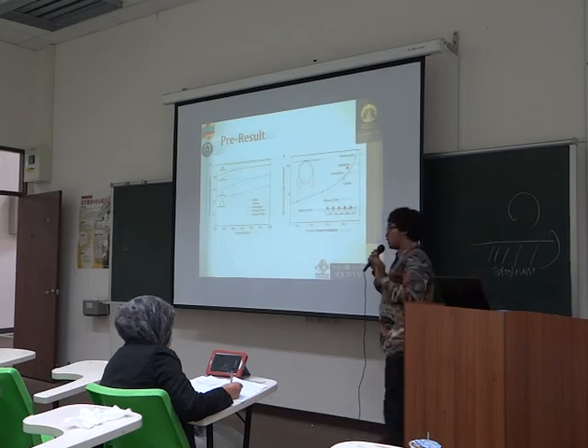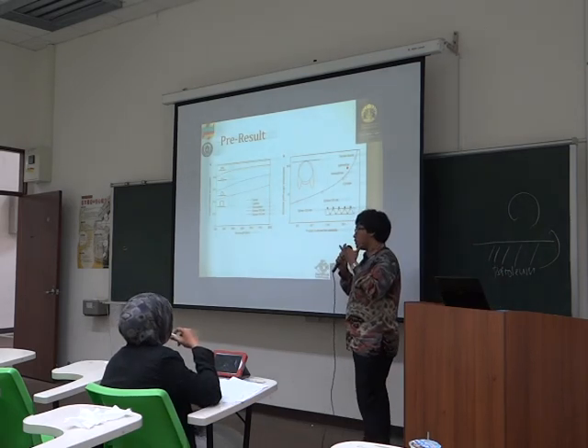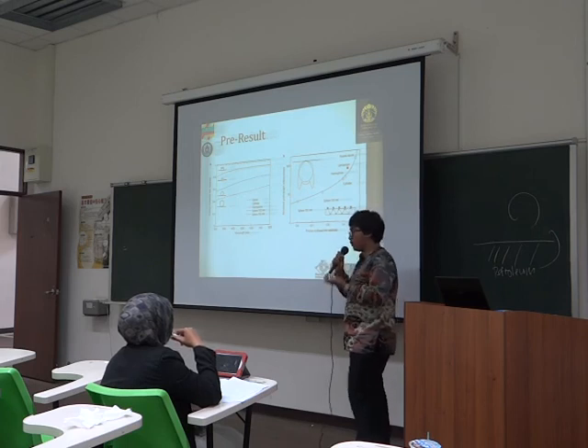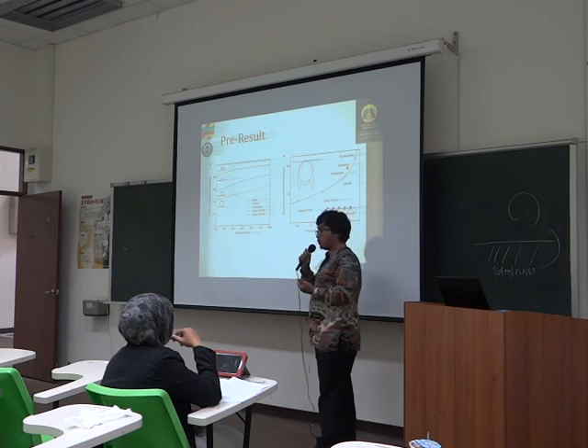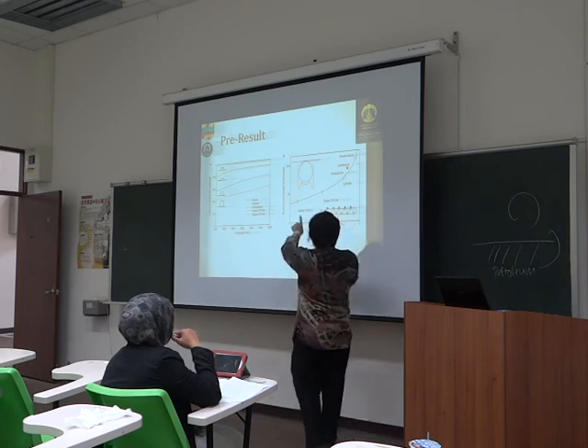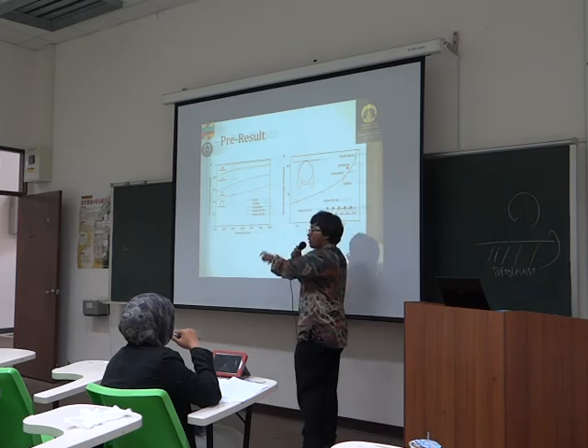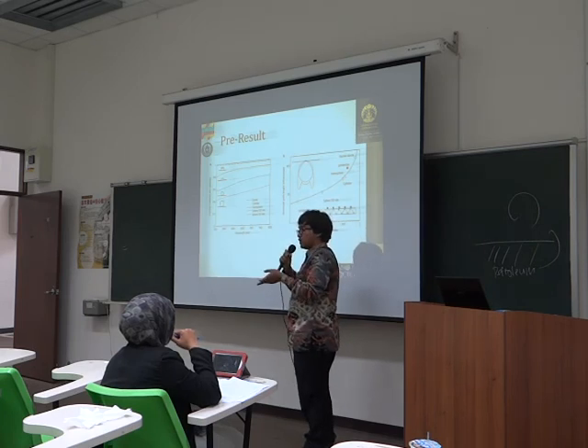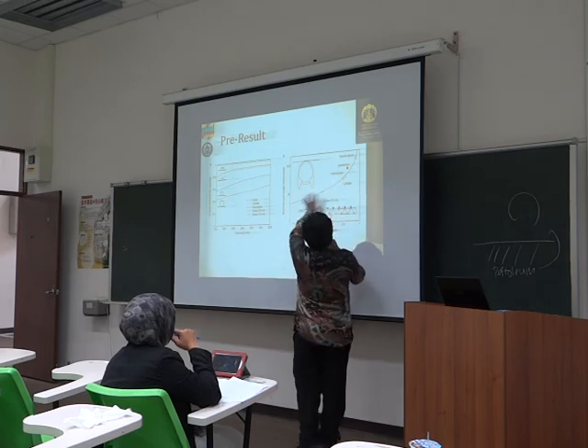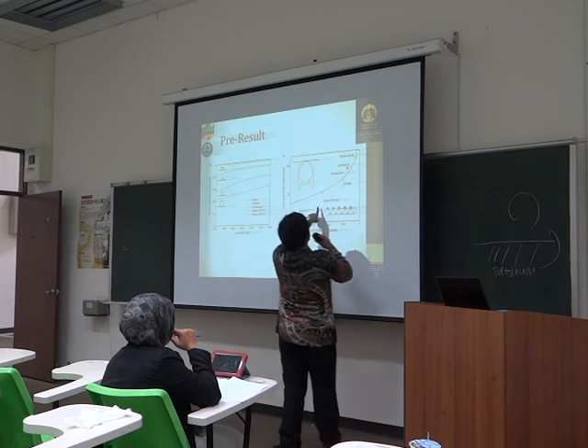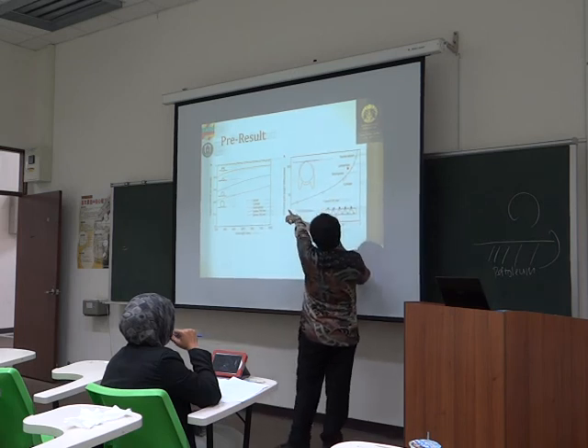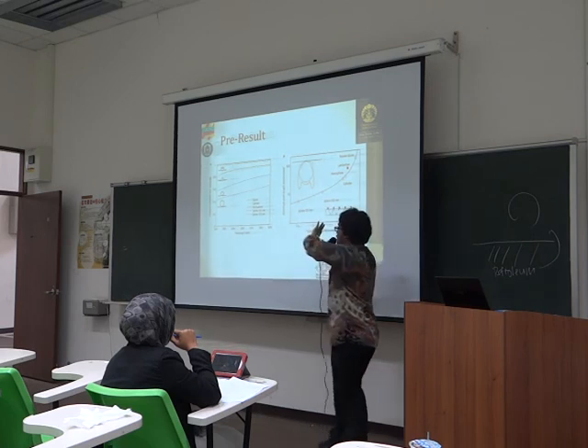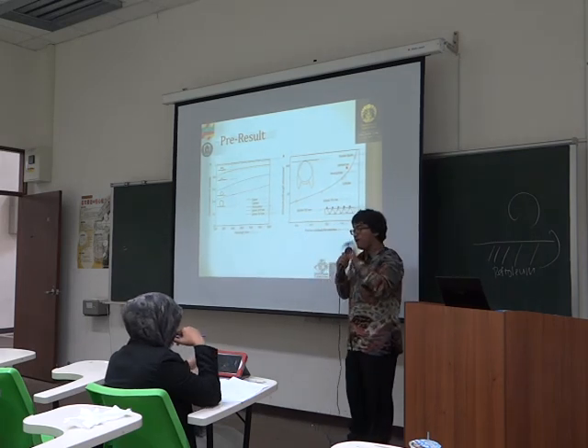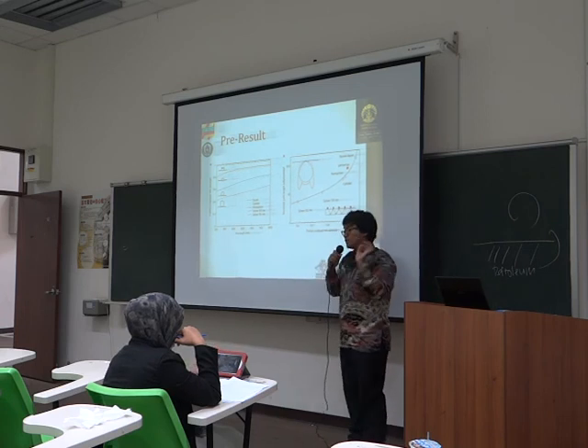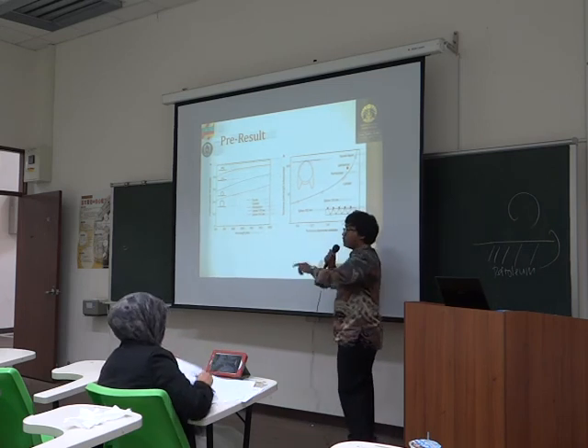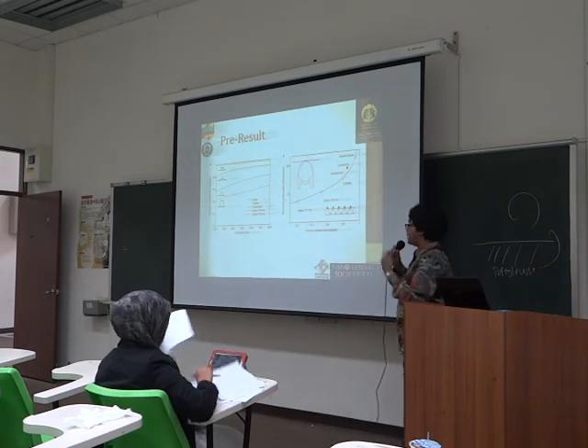Also, we don't only consider the size, we also use the shape of the nanoparticle. Because of the research of Professor Atwater at Caltech, Pasadena, we say that the shape of the nanoparticle contributes to the efficiency of surface plasmon resonance. Here we can get this graph, showing that a sphere of 100 nanometers can contribute to a maximum path length of about 10. So the size and the shape both have an effect on the surface plasmon resonance. So we use both of them to increase the efficiency of the solar cell.